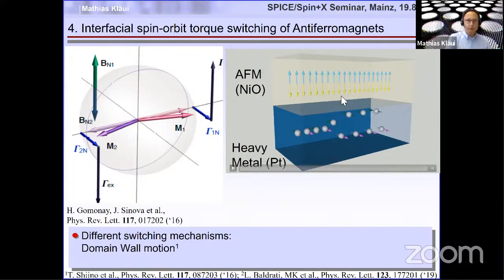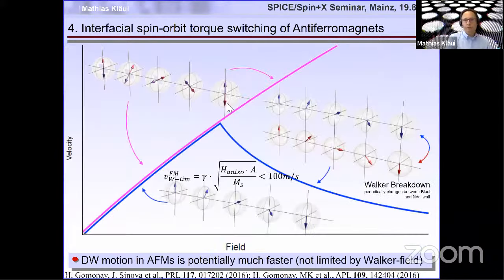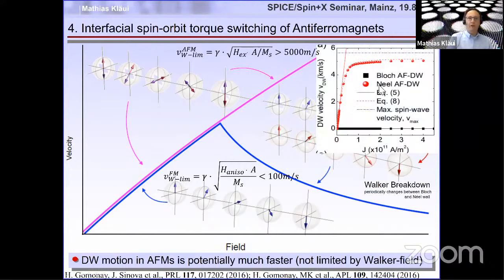This was also predicted here by Kyung-Jin Lee in this paper here. And the thing is that this is quite nice because it leads to very fast domain wall motion. So it was predicted that in these antiferromagnets, you don't have the problem of a Walker breakdown, which you get in ferromagnets, which limits your velocities to 100 meters per second. But actually, in antiferromagnets, the speed can be a few thousands of meters per second, limited just by the magnon maximum velocity in these systems. So this is very nice.